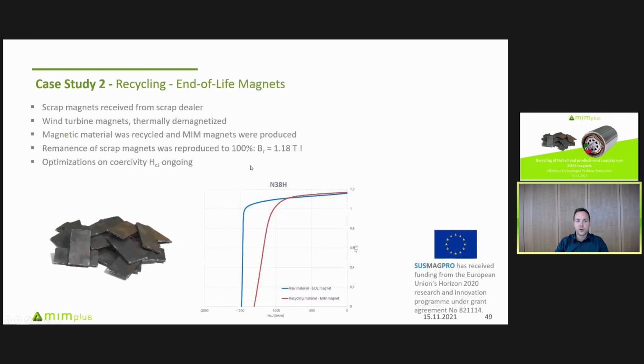The second case study I'd like to show you is recycling of end-of-life magnets, where the magnets were received from a scrap dealer. These were wind turbine magnets, thermally demagnetized, and the magnets were processed to powder and then used in the whole MIM process to produce MIM magnets. For that case, it's the N38H alloy. We were successful in reproducing the remanence to 100%. It was here 1.18 Tesla, while the optimization of coercivity is still ongoing, which is more an annealing and thermal treatment process here.